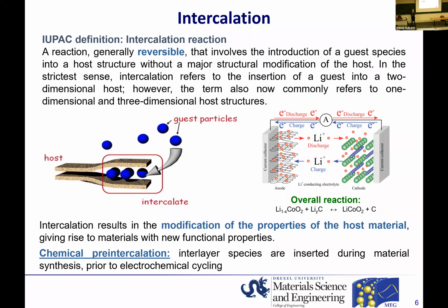So intercalation is basically a type of chemical reaction that involves two players. First, it's a host material with a given structure. And then there are guest species. In the case of energy storage devices, these are most commonly inorganic ions. So what's happening in the course of this intercalation reaction is that guest species are being inserted into the crystal structure of the host material without any major modification of the structure of the host. For example, if our host is a layered material, when we intercalate certain species, the layered structure doesn't transform into anything else. The only thing that can be changing is this interlayer distance.